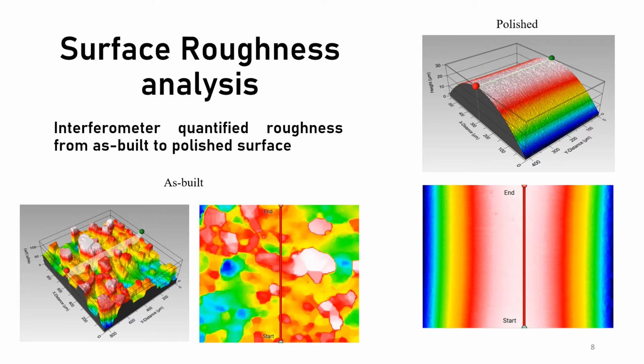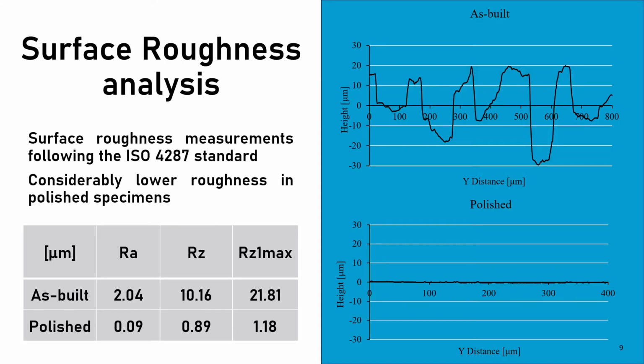Through an interferometer, we quantified the roughness from as-built to polished surface. We can see here the rough surface obtained by the selective laser melting method. Well, after the polishing sequence, we have a mirror-like surface with very low roughness. From the interferometer results presented in the previous slide, we quantified the roughness following the ISO 4287 standard. We can clearly see that polished specimens have a much lower roughness than the as-built specimens.